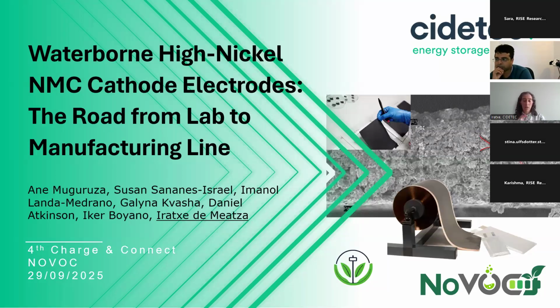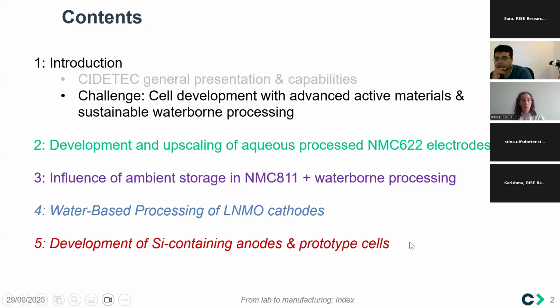water-based slurries for wet electrode coating manufacturing processes, particularly when upscaling, where you start to observe more issues, since anode manufacturing is already an industrial standard working with waterborne slurries. If anyone has curiosity on that, containing silicon, there are some particularities when introducing silicon in carbon-based anodes and water-based processing, but the major challenge is on the cathode side.